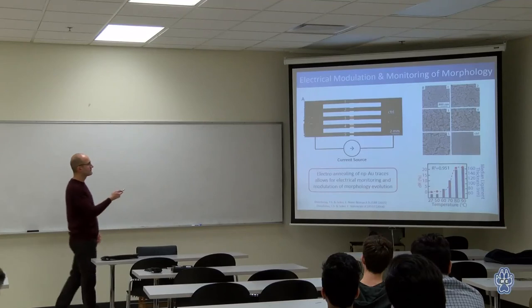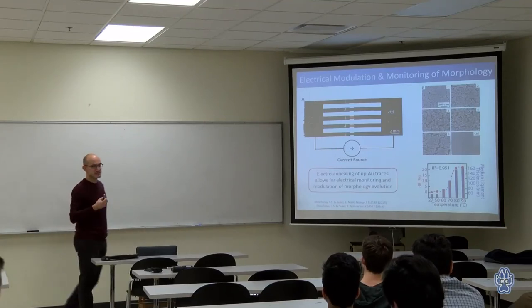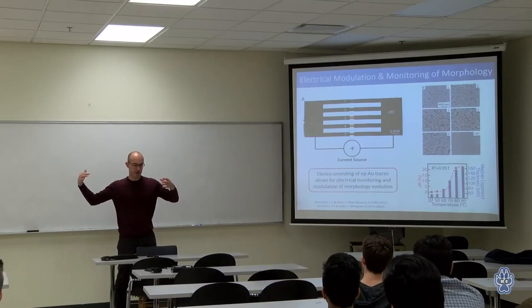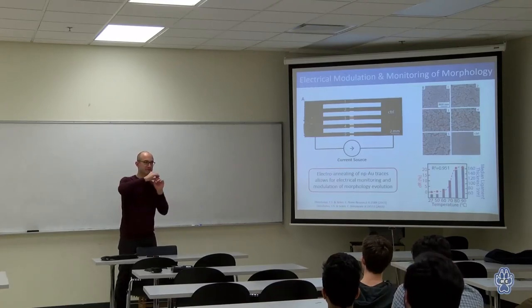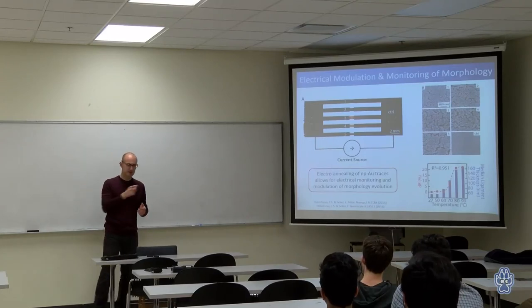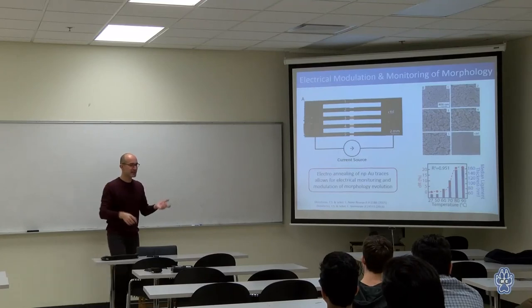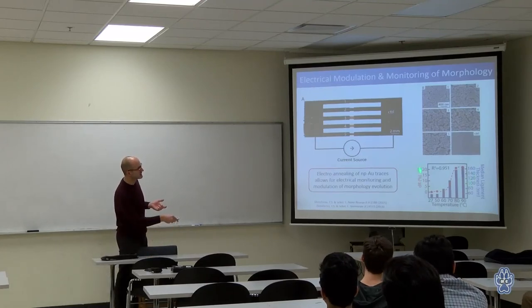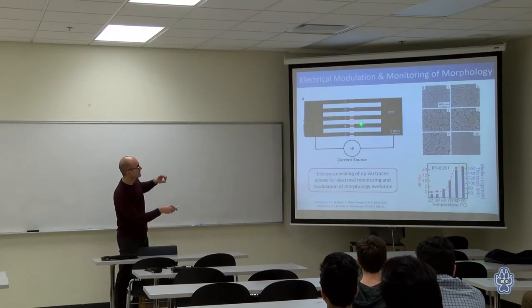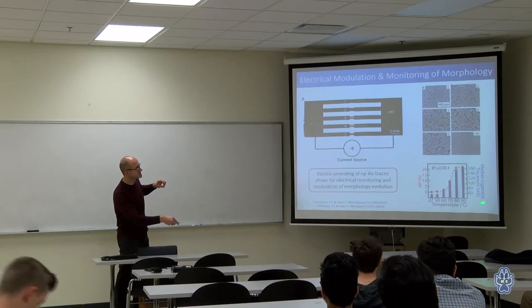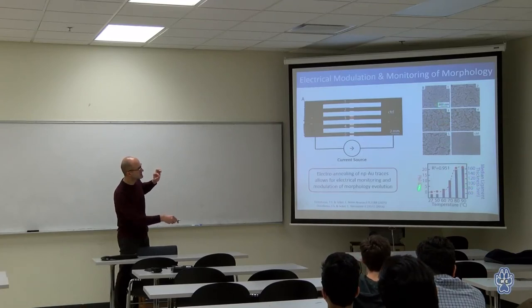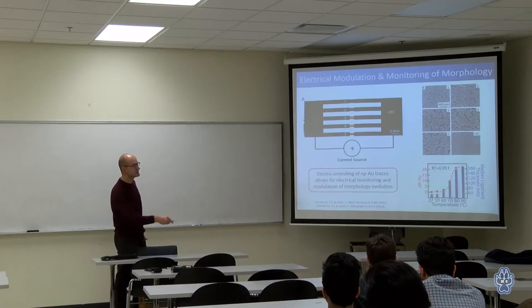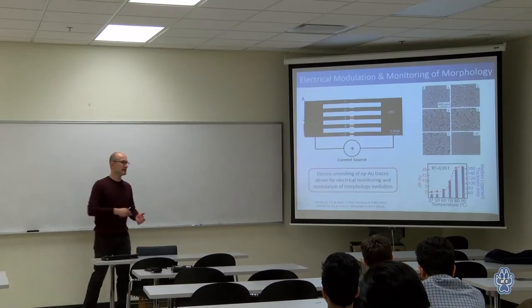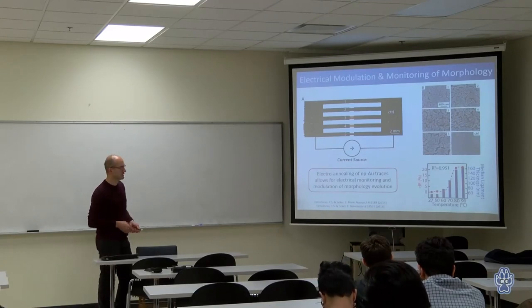Another advantage here is the electrical resistance. As you may imagine, this is basically the current flowing through that porous path. It's a lot of tiny wires in 3D carrying the current. So if you change the architecture of those by annealing and coarsening them, you're actually changing the resistivity of that 3D electrode. And that correlates very well with morphology. So you can keep track of the resistance change due to the morphology or structure change of the electrode. This is the thickness of these individual ligaments. This is the resistance change. So now you can dial in the morphology you want, and you keep track of the resistance, and you can get that morphology that you're interested in.